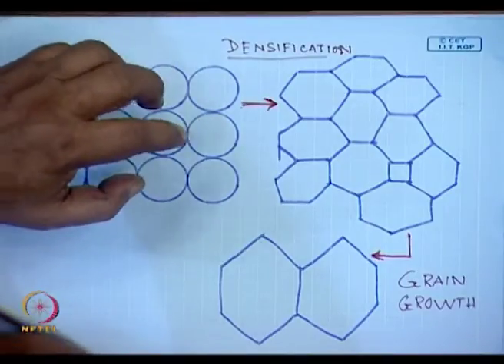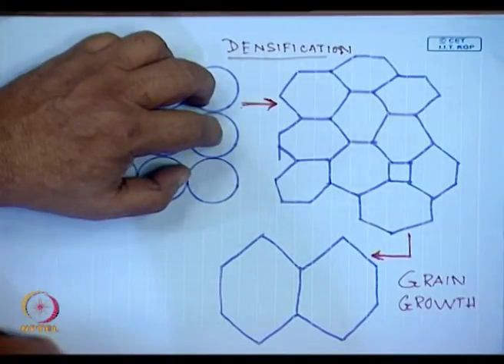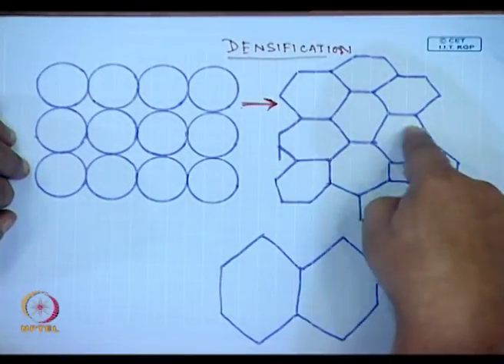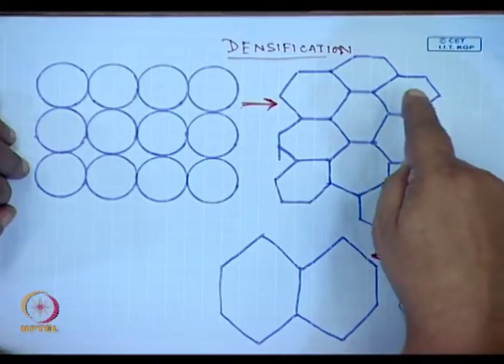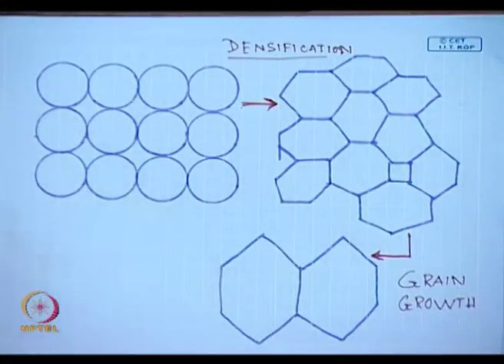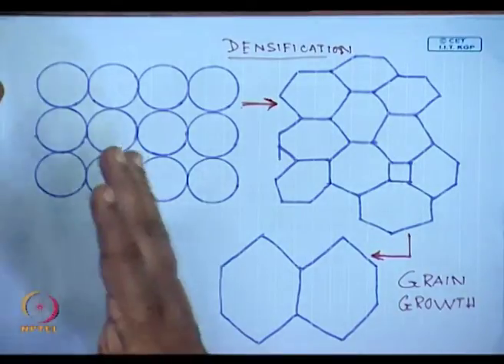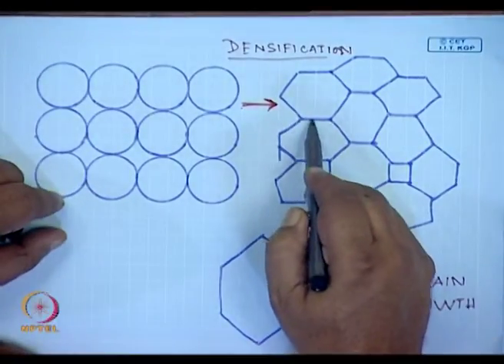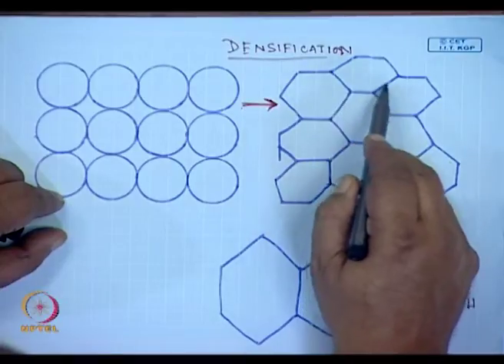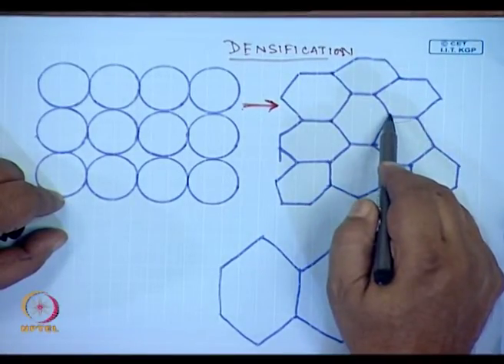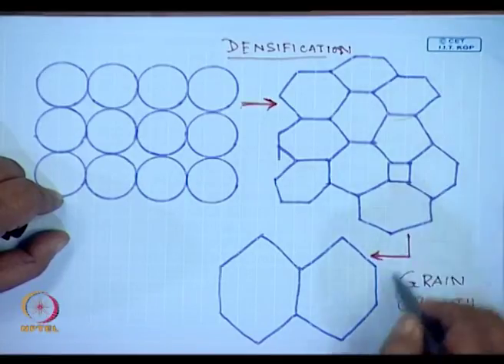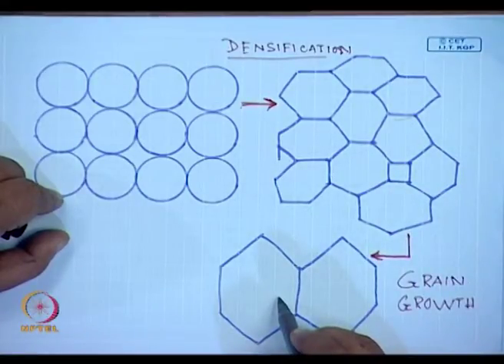Densification: here are some idealized spherical granules of ceramics which have been pressed and heated. First of all, here what we see is the grains have grown. Yes, there is a reason to draw even these 4-sided structures, as will become apparent later. So what has happened is you do not see any porosity along the grain boundaries. So here densification has occurred, and on further heating, grains have grown very large.